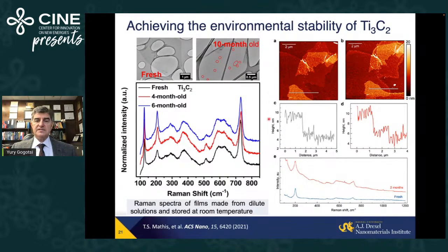A number of MXenes can be hydrolyzed in air, and those carbides and nitrides can oxidize at the end of the day. However, if you control defect concentration in materials and achieve materials with high stoichiometry, as we discussed for the first time in this paper in 2021, you can get materials with very, very good stability, which for months, stored in dilute solution in a closed vial, don't really change.